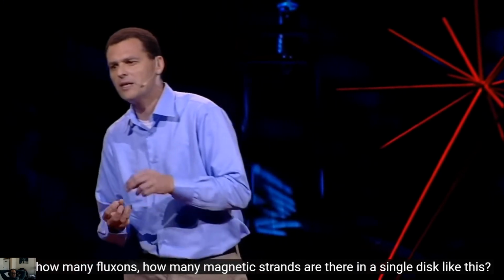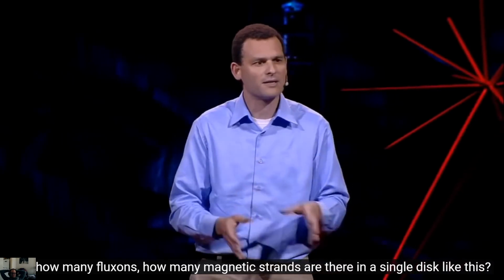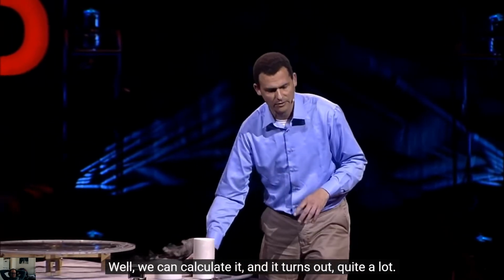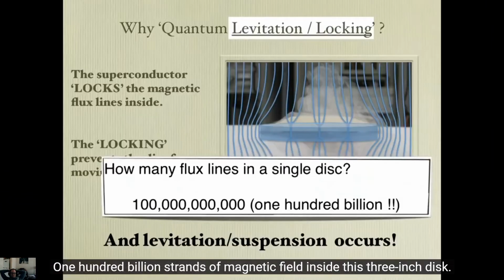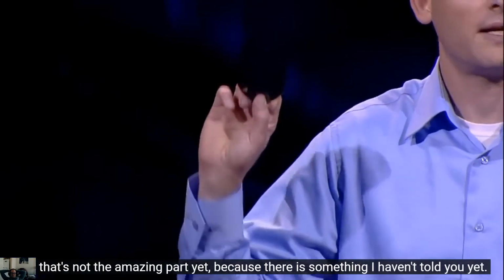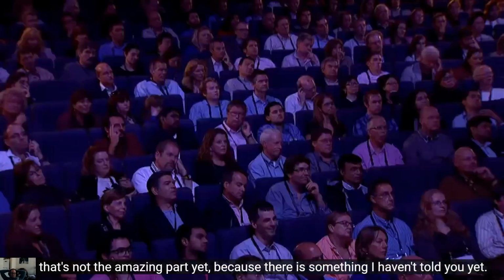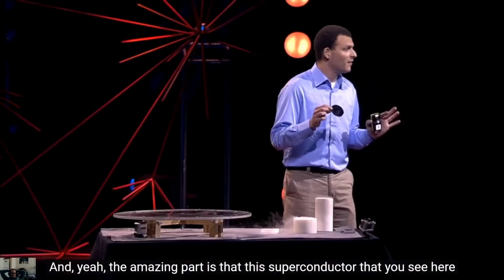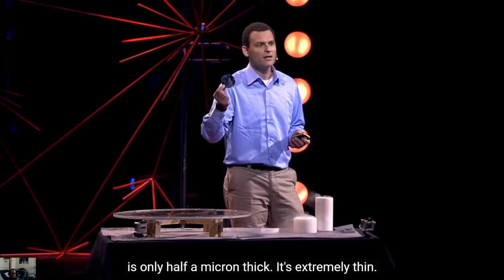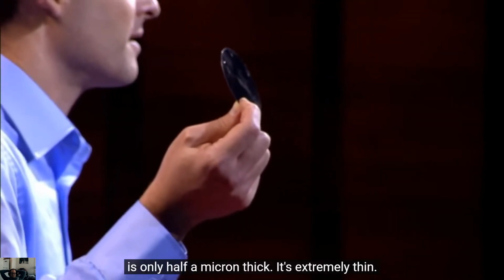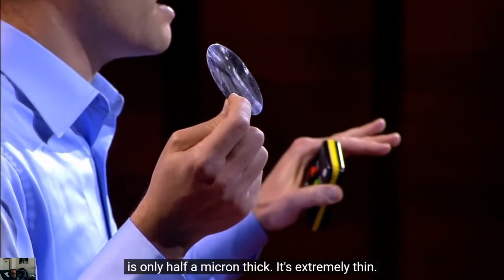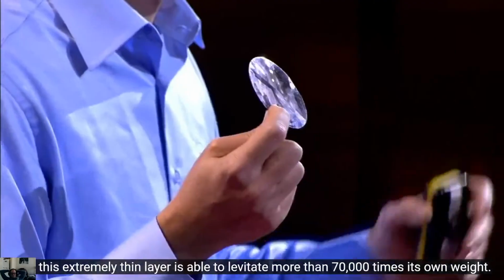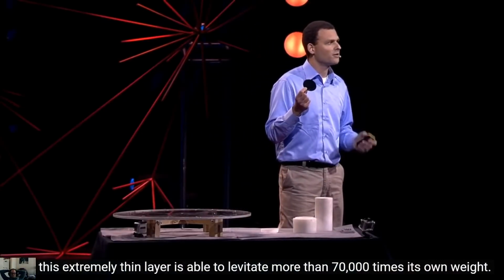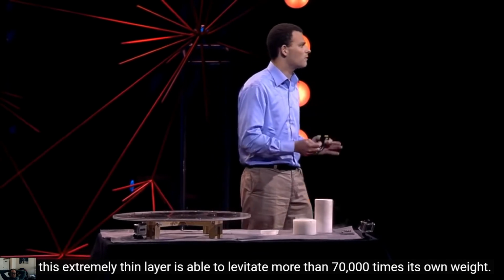So we have quantum locking and we can levitate it on top of this magnet. But how many fluxons, how many magnetic strands are there in a single disk like this? Well, we can calculate it, and it turns out quite a lot: 100 billion strands of magnetic field inside this 3-inch disk. But that's not the amazing part yet, because there is something I haven't told you yet. The amazing part is that this superconductor that you see here is only half a micron thick. It's extremely thin, and this extremely thin layer is able to levitate more than 70,000 times its own weight. It's a remarkable effect. It's very strong.